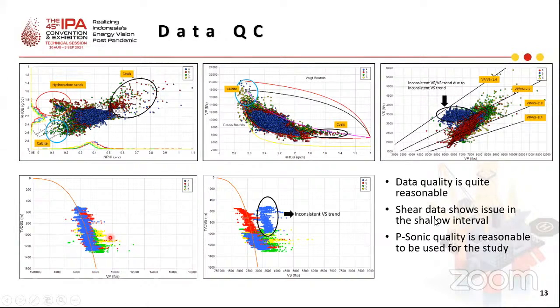For further clarification, we try to do the depth trend analysis using the P-sonic or the VP curve. So in general, VP follows the correct depth trend for all the wells. But the crossplot of VS versus TVDSS shows us that well A in blue color has an inconsistent VS trend. This confirms that the shear data in well A is spurious and cannot be used directly for seismic reservoir characterization work. But for the purpose of our study, where we are trying to compute the porosity, we just require a reasonable quality P-sonic curve, which is present in here.